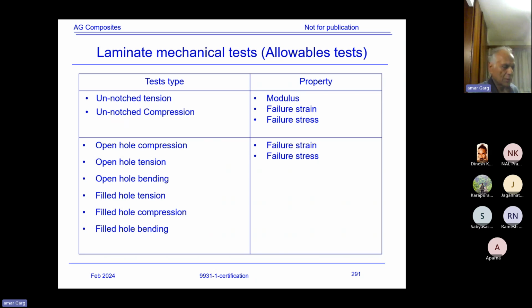So I'll make the quasi-isotropic coupons for hot wet conditions, test it in hot wet condition, determine the value. And once you determine the value for that, then using the value of that hot wet condition and room temperature, compare that, what is the ratio, knockdown. So using that knockdown value, that's a 20% reduction, suppose. So you will apply that 20% knockdown value for hot wet condition over your design value.